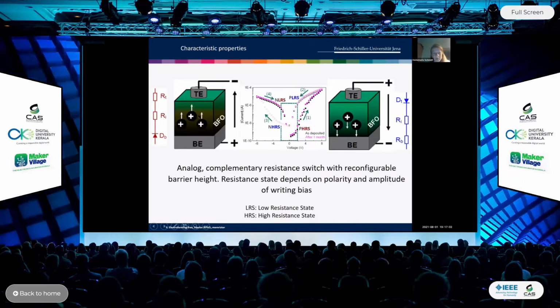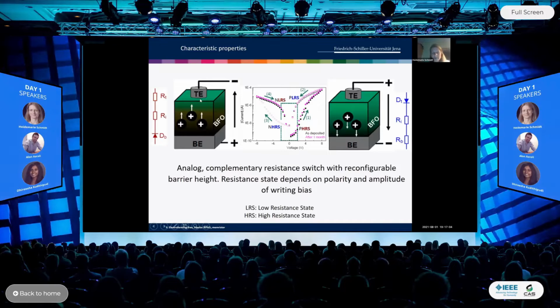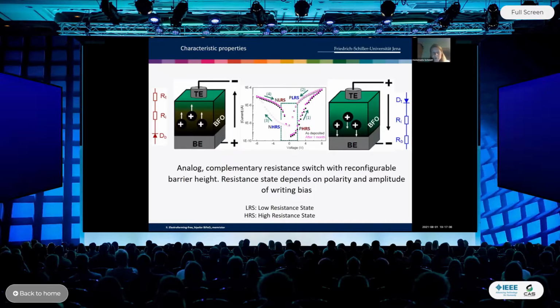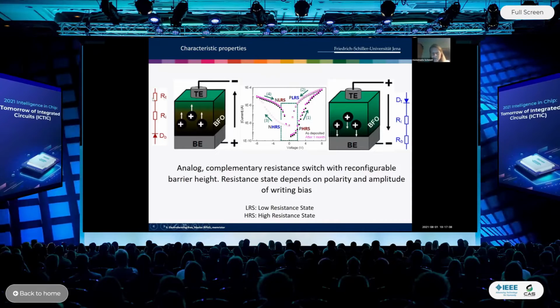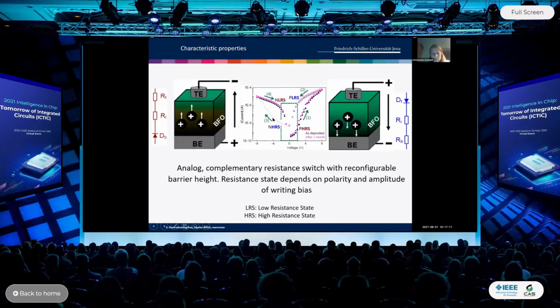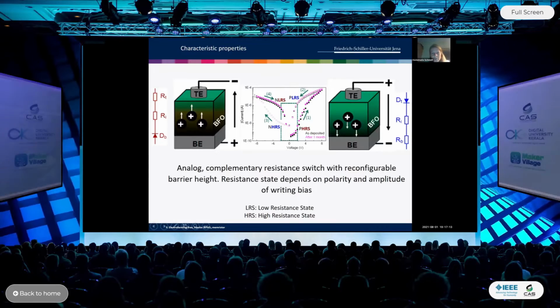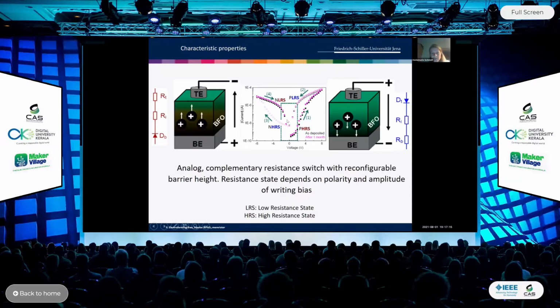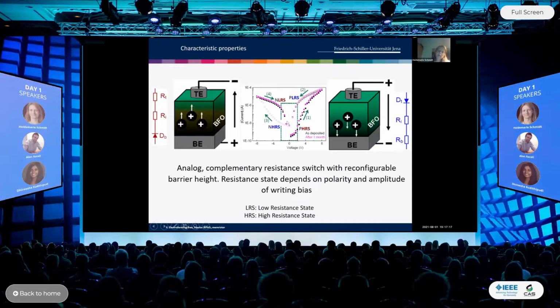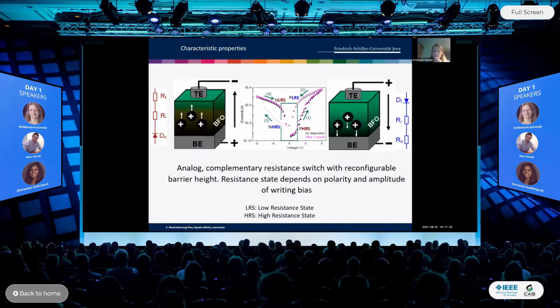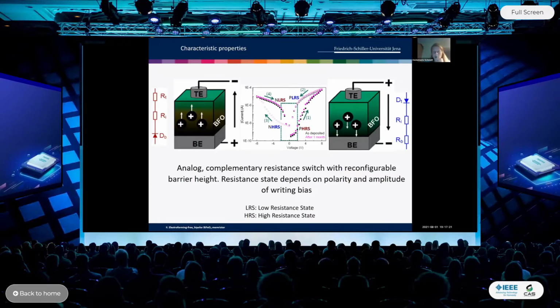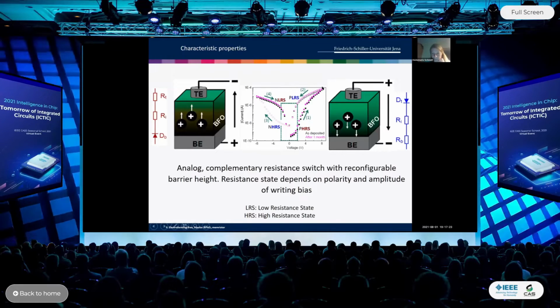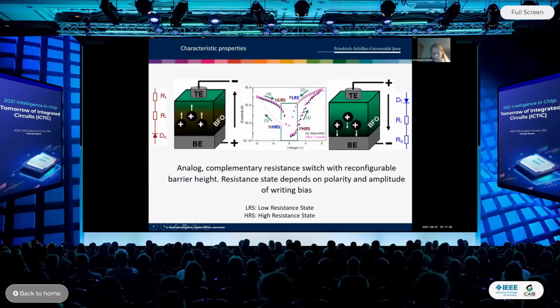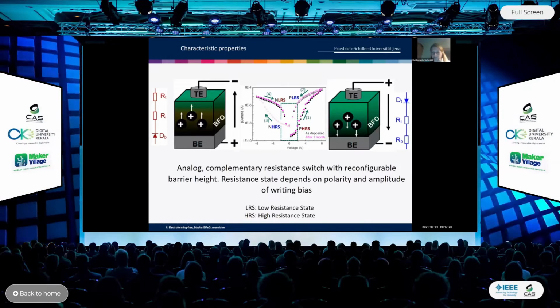For example, here we attract the oxygen vacancies to the top electrode. The top electrode becomes non-rectifying, as you can see here, and then it switches from the high resistance state back to the low resistance state. Okay, and now it depends, as I already said, on the polarity of the writing bias, which state the system will be in.